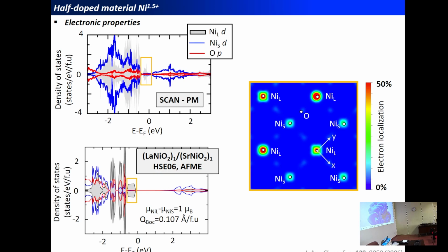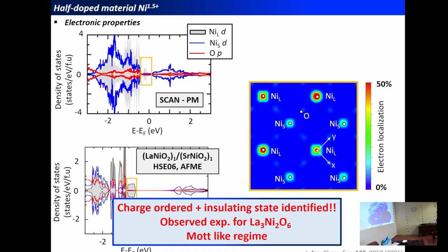And if we perform a hybrid DFT calculation using a smaller cell, because the full cell is too big for hybrid DFT, you see that the density of states is very similar between the 2 solutions, but now with the hybrid DFT calculation we have a sizable band gap opened in the material. We still have the asymmetry of the 2 types of nickel cations, and we still have a sizable breathing distortion appearing in the ground state of the half-doped system. And therefore, in the half-doped systems, we identify a charge-ordered state which is insulating, and this type of charge ordering has been observed experimentally for the reduced Ruddlesden-Popper material.